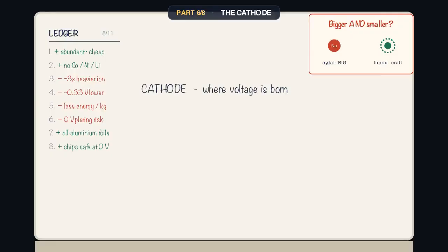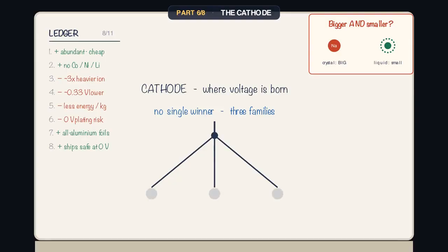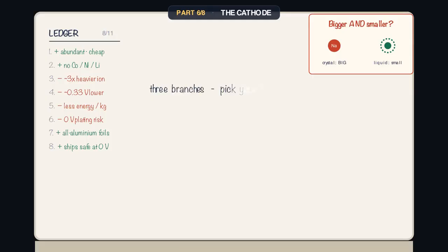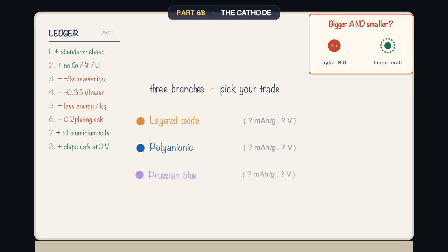The cathode, the positive host where sodium lives when the cell is charged, and where the voltage is really born from a transition metal changing its oxidation state. And here's the twist. Unlike the anode, there is no single winner. 3 whole families compete, each a different bargain. Let's grow the family tree. 3 branches: layered transition metal oxides, polyanionic compounds, phosphates and fluorophosphates, and Prussian blue analogs, iron cyanide cages. Highest energy, or highest voltage and life, or lowest cost and fastest, pick your trade. Watch each branch fill in.